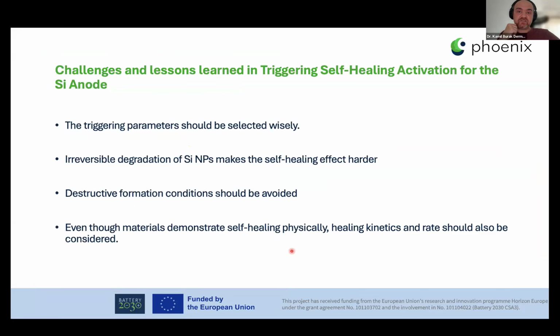So the challenges and the lessons learned in the triggering and self-healing activation for silicon anodes, if I can wrap up: the triggering parameters should be selected wisely. These are really parameter-affected and parameter-vulnerable mechanisms, and we really need to investigate more on that. The irreversible degradation of the silicon nanoparticles actually makes the self-healing effects even harder. Destructive formation conditions should also be avoided. And even though the material demonstrates self-healing physically, as we showed, the healing kinetics and rates should also be considered to really reflect the self-healability in the electrochemical metrics.